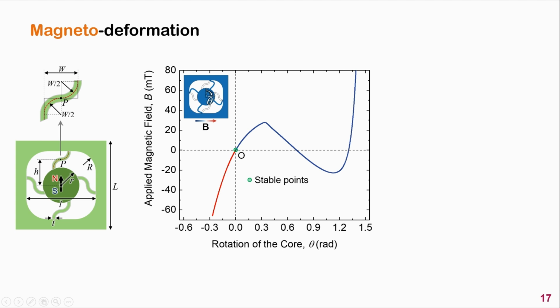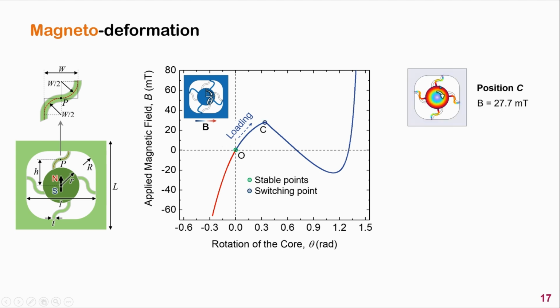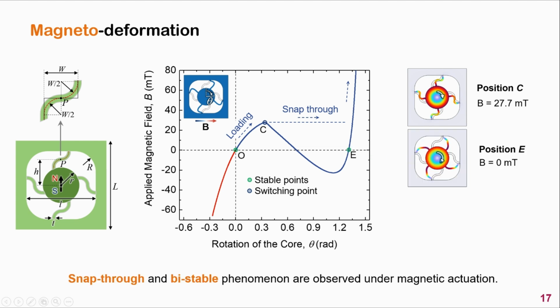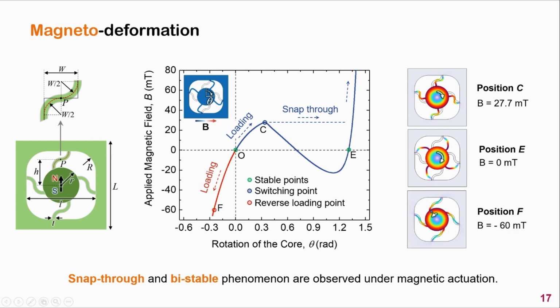rotation angle of the mass core, and the relationship between the rotation angle of the mass core and the intensity of the applied magnetic field. As shown here, when we apply a magnetic field in the positive x direction, the curved beams will be compressed. Then, at a critical point, the snap-through behavior is observed. After that, if we reduce the intensity of the magnetic field gradually to zero, the system will be stable at its second stable state. By contrast, when we apply a magnetic field in the negative x direction, the beams will be stretched. In this case, the system is monostable.